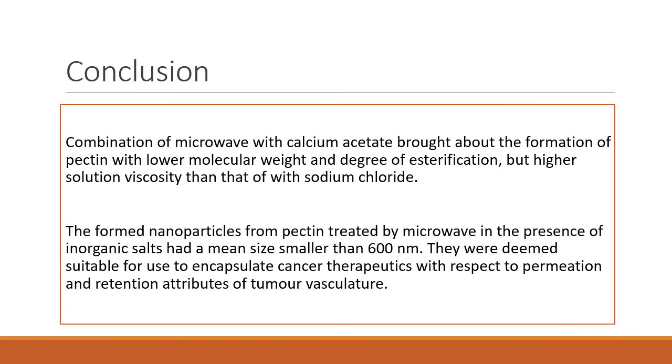In conclusion, combination of microwave with calcium acetate brought about the formation of pectin with lower molecular weight and degree of esterification, but higher solution viscosity than that of with sodium chloride. The formed nanoparticles from pectin treated by microwave in the presence of inorganic salts had a mean size smaller than 600 nanometer. They were deemed suitable for use to encapsulate cancer therapeutics with respect to permeation and retention attributes of tumor vasculature.